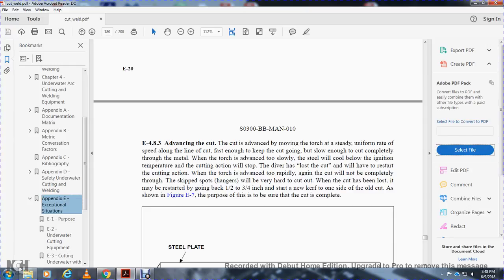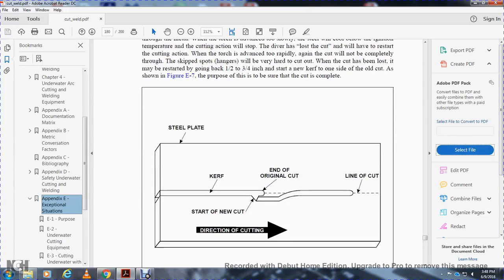If the torch is advanced too rapidly, the cut will not go completely through, and the skipped spot will be very hard to cut. When the cutting has been lost, it may be restarted by going back 1/2 inch to 3/4 inch and starting with a new kerf on one side of the old cut, as shown in figure E7. The purpose of this is to be sure that the cut is complete. Figure: shift the direction of the cut, the steel plate, the curve, the start of the new cut, the original end of the cut, and the line of cut.